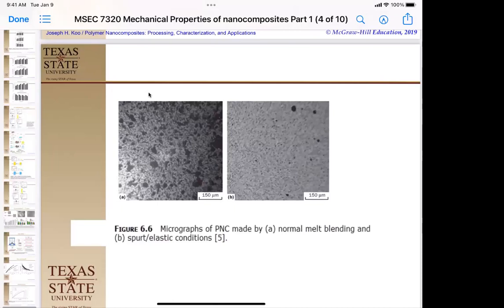And the unit was doing what we call spurt conditions on an extruder. And in the spurt conditions, they found out that they had much better dispersion. Okay, so in an extruder, you typically run at a fixed temperature, a fixed speed, and the stuff going in, the stuff coming out all go at the same rate. So you think of the pressure going into your extruder, it's very low at the beginning, then it starts melting and mixing, it starts rising, and then you start necking it down to where it's about to come out of the fiber guide, and that's where it's its highest pressure. And as soon as it gets out of that nozzle, boom, it drops in pressure, right? So you're looking at increasing shear all the way to the die end and then it stops. Okay, and then if you're drawing out, that's a secondary shear effect, but we're just talking about the pressure.